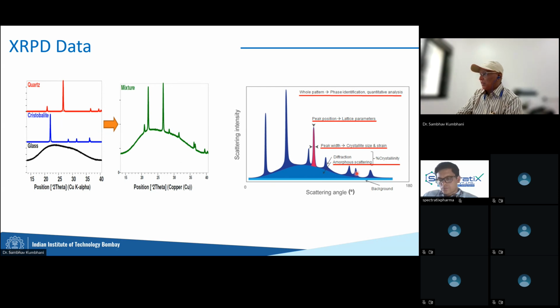And finally, we can get how much is crystalline and how much is amorphous. So here's a cool one. If you don't take away anything else from today, you can take this simple lesson away. In an XRD spectrum, if you have a flat, horizontal background, you basically have no amorphicity in your sample. And if you have a hump in your diffractogram, then you have amorphous material in your sample.